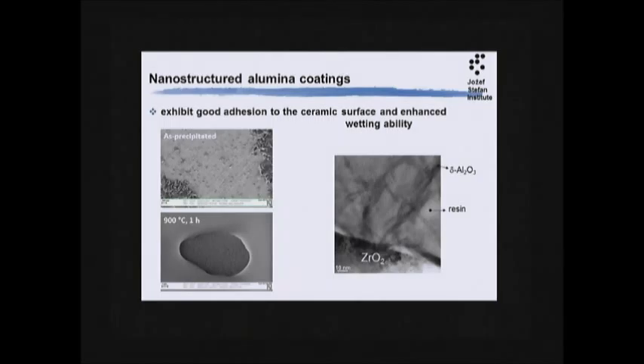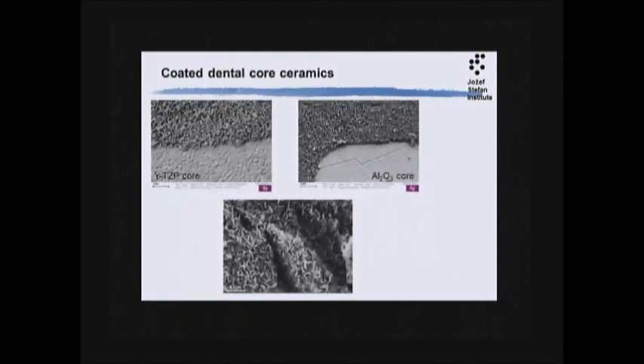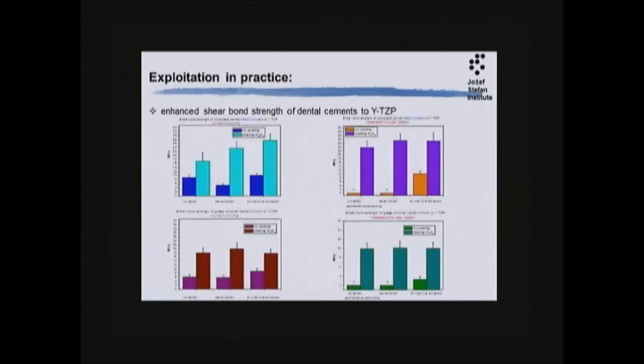And another good message is that the cements or glues, perhaps this was a glass ionomer, that's very good. The organic part, that's very good. Those coatings, you'll find them everywhere. So how it looks like on zirconia, on alumina. This is on sandblasted alumina. So it goes inside from everywhere. And Peter Jonica tested two sorts of cements, and in both cases he found a much better adhesion even after thermocycling.